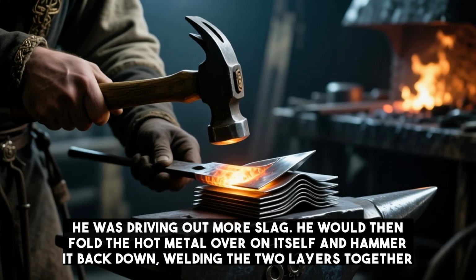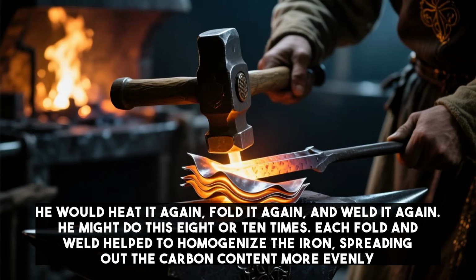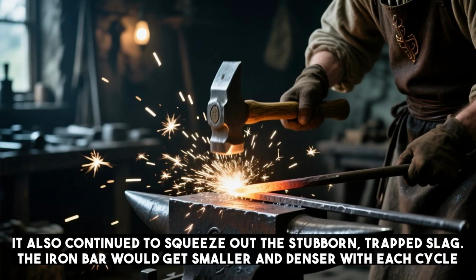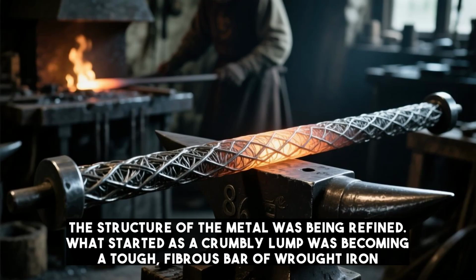He would then fold the hot metal over on itself and hammer it back down, welding the 2 layers together. He would heat it again, fold it again, and weld it again. He might do this 8 or 10 times. Each fold and weld helped to homogenize the iron, spreading out the carbon content more evenly. It also continued to squeeze out the stubborn, trapped slag. The iron bar would get smaller and denser with each cycle. The structure of the metal was being refined. What started as a crumbly lump was becoming a tough, fibrous bar of wrought iron.